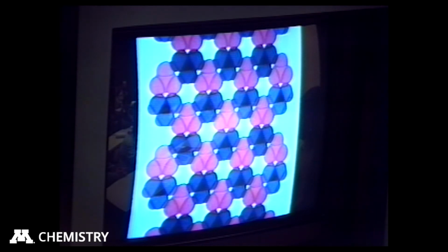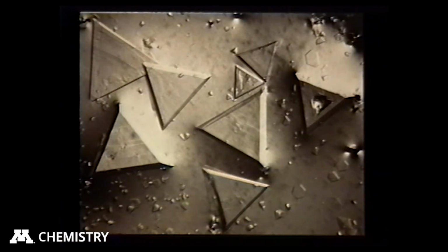Now, something that's very interesting about this is that there is a real 3-fold axis right here in each of these centers. But the 3-fold axis does not propagate throughout the crystal. So the crystals are monoclinic. They're not trigonal, even though each individual plane has a real 3-fold center. And what happens is that as these planes pack, they just slip, so that 3-fold axis is not in registry with the one of the next layer. All right, so you end up with a monoclinic crystal that is pseudo-trigonal, and this is what the crystals look like. They look like beautiful trigonal crystals.